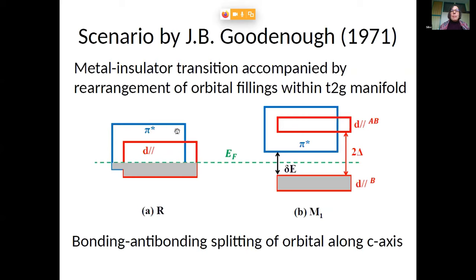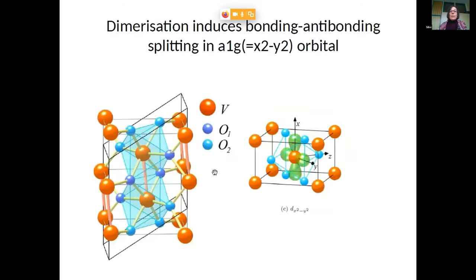And then his proposal was that the dimerization leads to a bonding-antibonding splitting of the D parallel combinations, and a little push up of the EG pi or pi star bands, which would then open up a gap again. So just to clarify, what we are talking about is this specific orbital here, the D parallel or A1G, that would then essentially do the job.